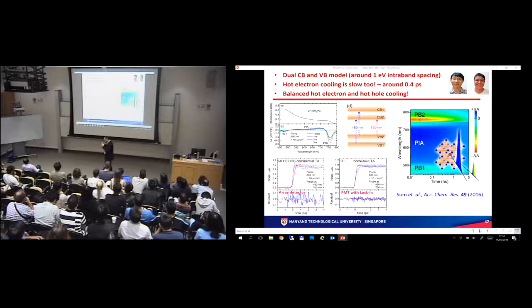Now, we continue, we did not lose focus with this idea. We continued over the years, from 2013, making sense of the band structure, trying to clarify and understand the structure. We kept this information of slow hot hole cooling at the back of our minds. We KIV'd the idea. Now, it becomes clearer to us that we are not only seeing a dual valence band, but we are also seeing a dual conduction band in this perovskite system. And this dual valence and dual conduction band coincidentally has an intraband spacing around 1 eV. In this work, we clarified that there's not only slow hot hole cooling, but the electron cooling process is also slow.